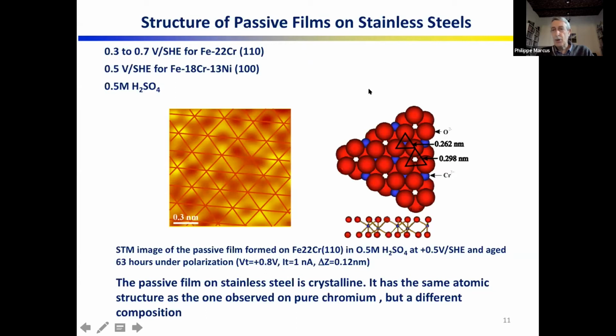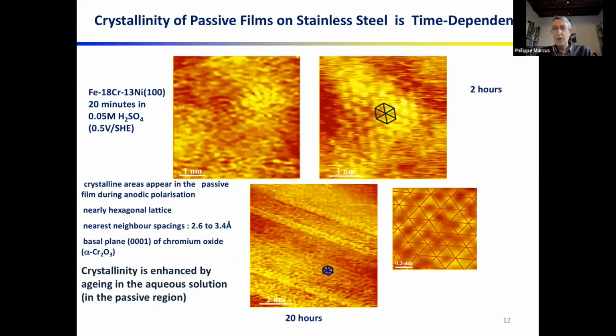It has the structure of alpha Cr2O3. But of course, there is not only chromium in it, there is also iron in it. The other point is that the degree of crystallization depends on time. These are images that were recorded at different lengths of time: short time, longer time, and even longer time.